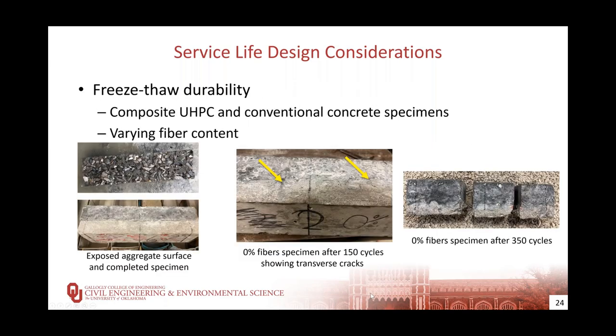However, a UHPC link slab or UHPC connection also includes an interface between the conventional concrete and the UHPC. Bond test results not presented here indicated good bond between the UHPC and conventional concrete, but composite UHPC and conventional concrete specimens were tested for freeze-thaw resistance to examine the effect of this interface on freeze-thaw durability. Conventional concrete specimens with an exposed aggregate finish were first prepared, and then the J3 non-proprietary UHPC was cast alongside the base concrete to create a composite specimen shown here on the bottom left.